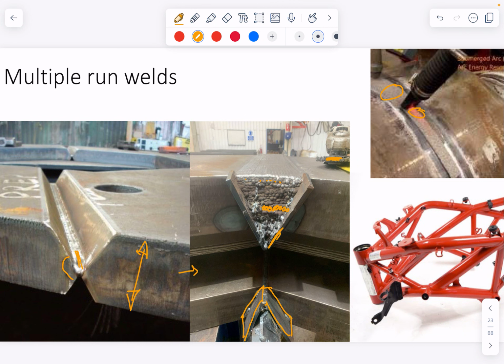The reason why we have these plates is to do with this heat coming out of the side of the plate here. If I simply start welding here and start going in and it's cold, the first little bit of this weld is going to be cold. I'm not going to get full good penetration. And it's much the same at the other end. I probably want to have a runoff plate. You can't see it here, but I would imagine there is a runoff plate at the other end. And once we've finished all these dozens and dozens of welds, we cut this bit off. And so we've got good quality weld all the way through the job.